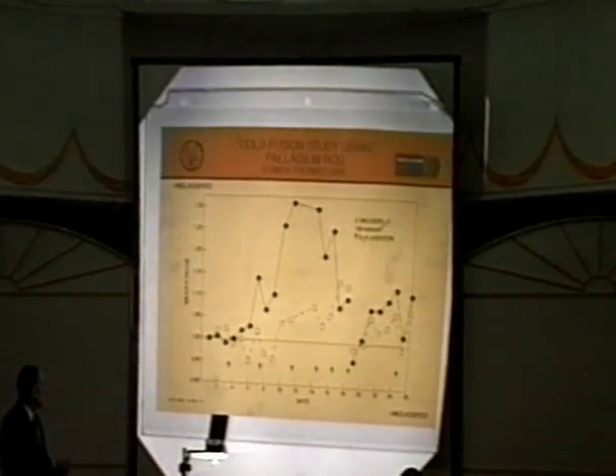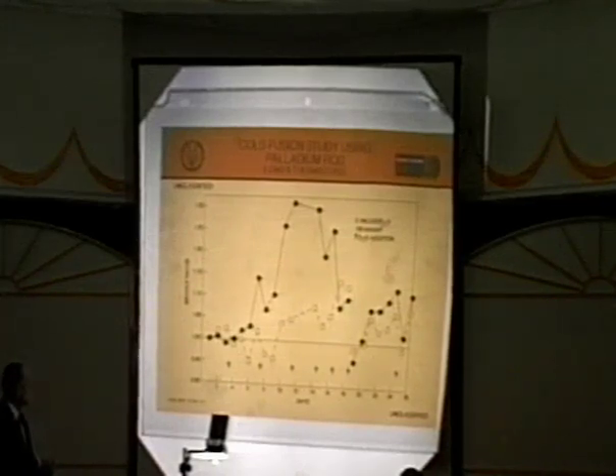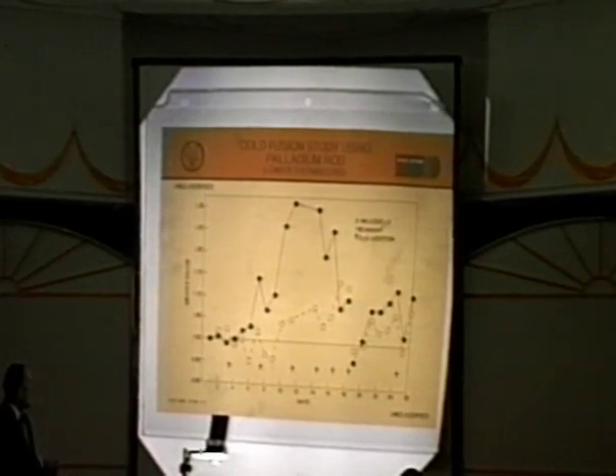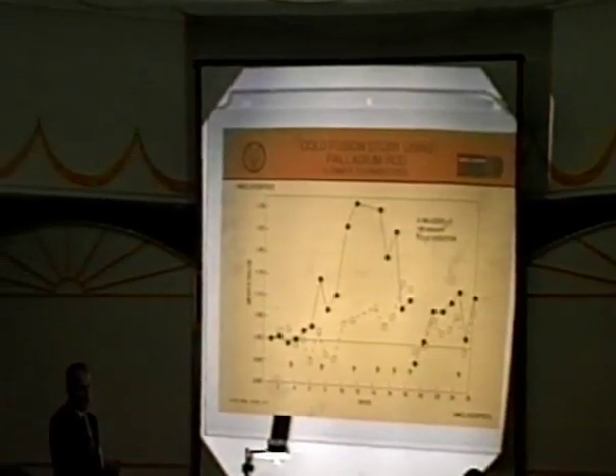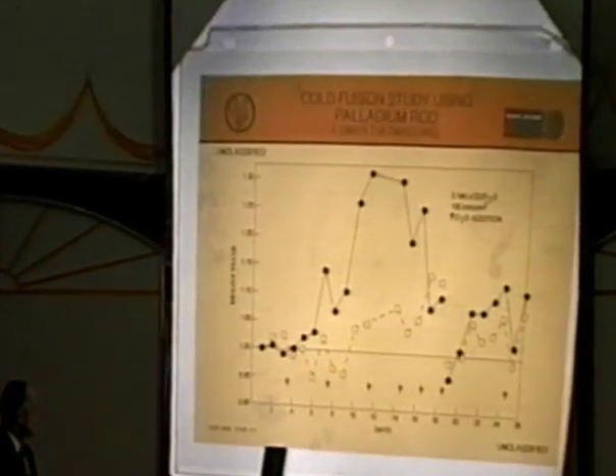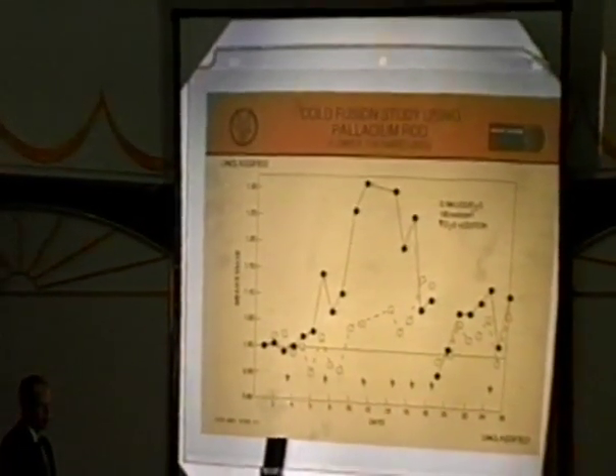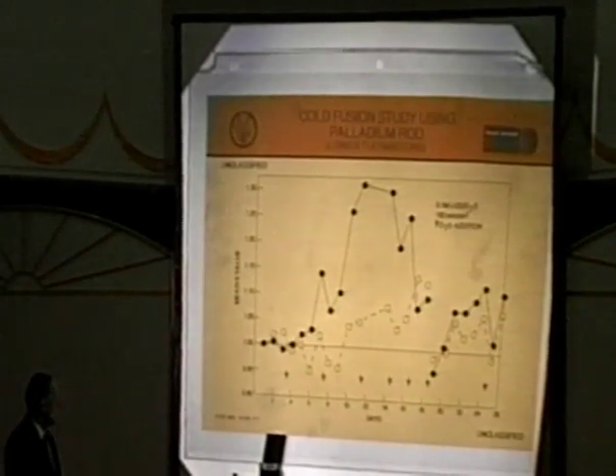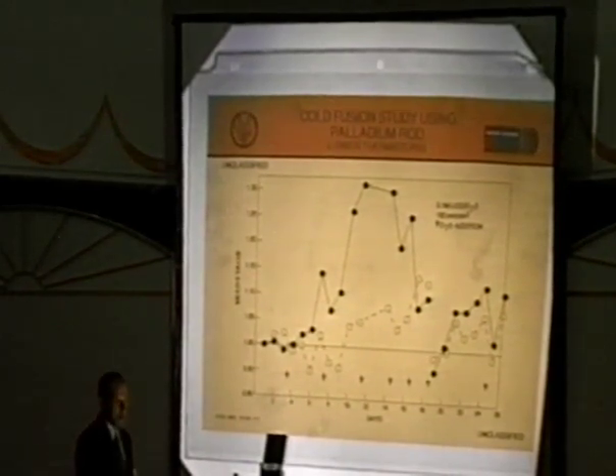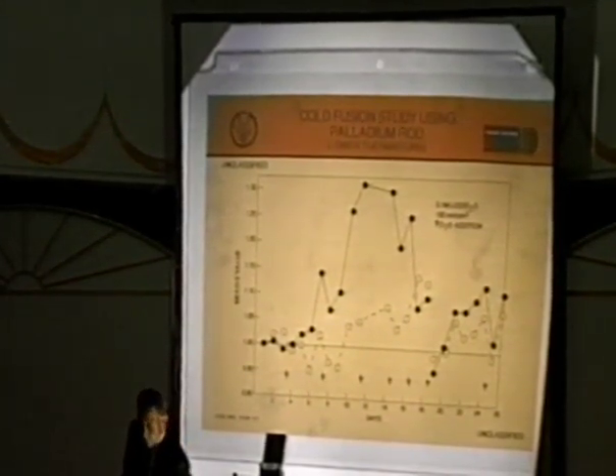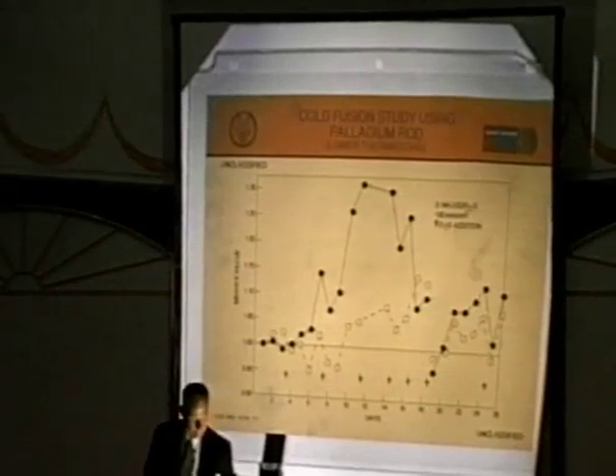Less excess heat in the second cell. This is cell, what we call cell A. This is what we call cell B. They're always run side by side in series. But you can see there's less heat in this cell, much more heat in this cell. We had a power failure here, which is probably good that happened because it deloaded for a few hours, and then when we start up again, we're back to break even. So that shows that it did go back to break even when the current was interrupted for a time period.